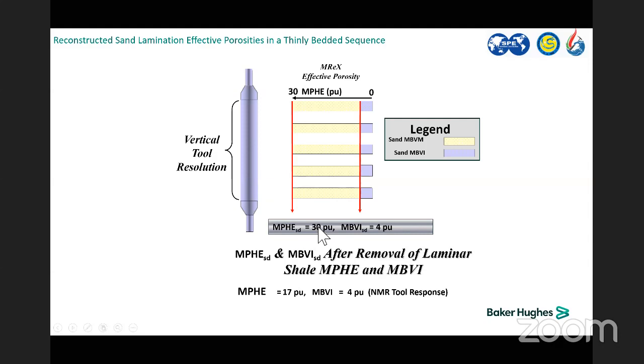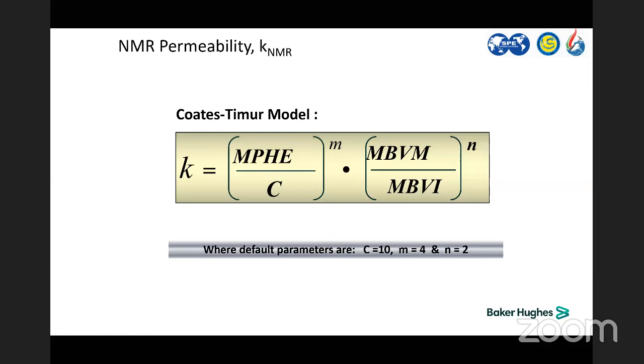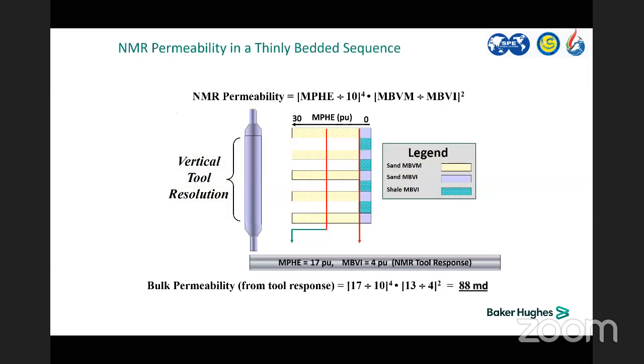The same applies for the permeability, because Baker Hughes is using Coates. Some of the others are using SDR, based on each company. But if you look at Coates, we are using the free fluids and the effective porosity. So after excluding the laminar shale and getting the real or close to the real sand porosity and effective free fluid volume, we are able to enhance the permeability from Coates as well. The conventional one shows about 88 millidarcy, based on the 17 pu conventional NMR porosity without excluding the laminar shale, and the constant of the Coates equation.